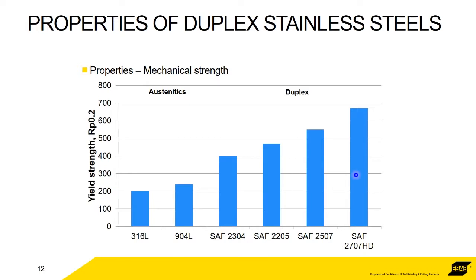In terms of mechanical strength, again, this is a fairly simple illustration. The 316 has a yield strength of around 200 megapascals. The lean duplex is 400, twice as good, fantastic. What I didn't mention before with lean duplexes is that they were really invented at a time when the nickel price was really, really high, because they use less nickel. So they're obviously cheaper. And for less cost of producing a lean duplex, you've got twice the mechanical strength. The duplex is around 460, super duplex up to 550.